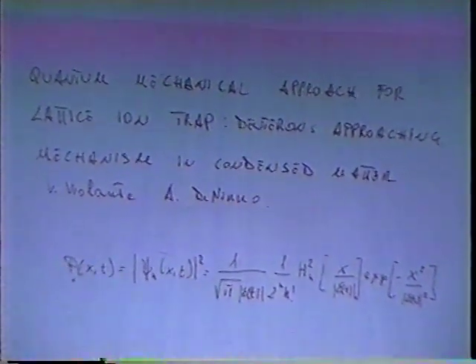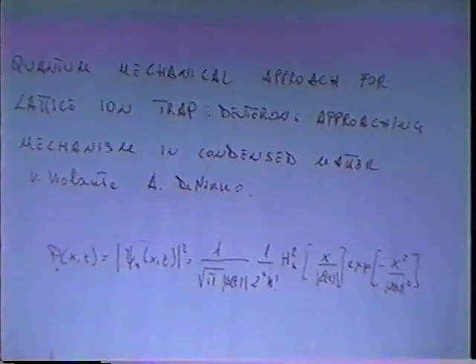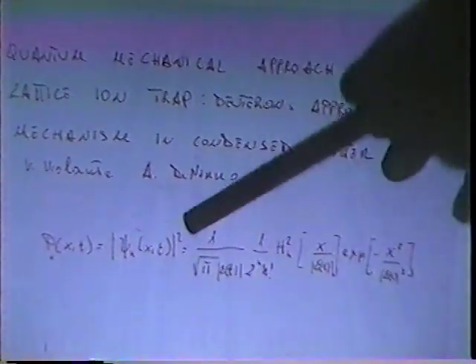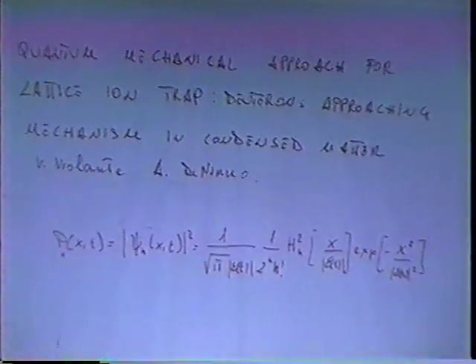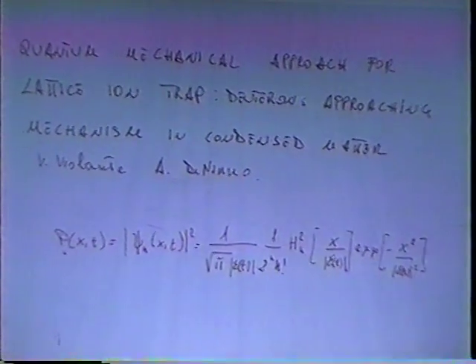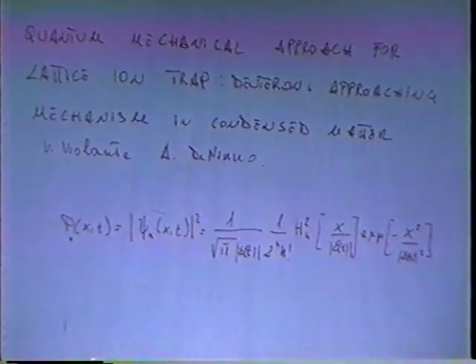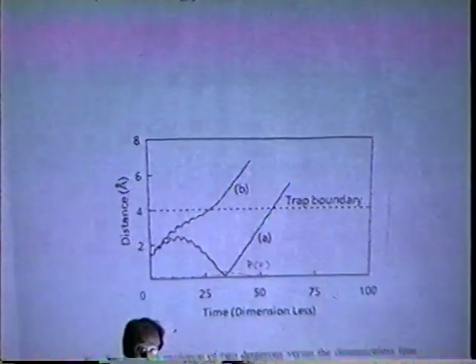And we can see that the probability to have a particle at a distance x from the central point of the trap where the other deuterons is located is a function of the function epsilon, which is the solution of the classical problem. So by introducing this expression for probability, we obtain a behavior like this, which is not in disagreement with the classical model.